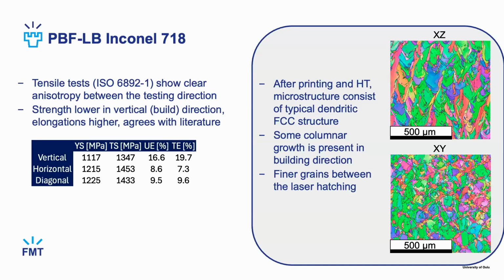If you check the microstructure, after printing and heat treatment, we still have this typical dendritic austenitic or FCC structure. Here the building direction is upwards, and this is X. You can see that there is maybe some columnarity, meaning that the heat input is relatively high. And when we look from the other direction in XY, you can see it is more uneven, and the columnarity is gone, of course, and you can see some finer grain growth in between the laser hatching tracks.